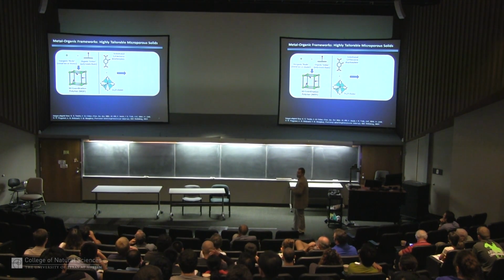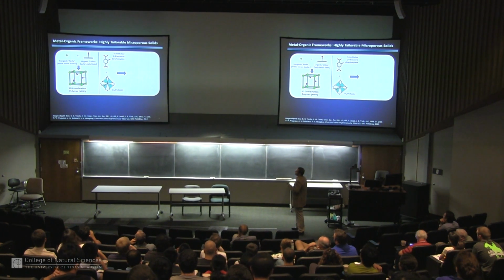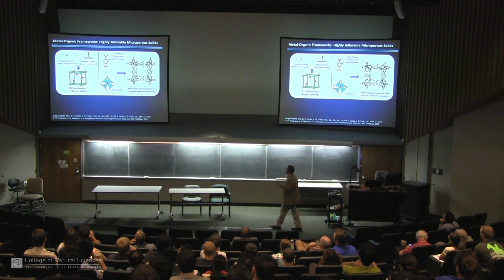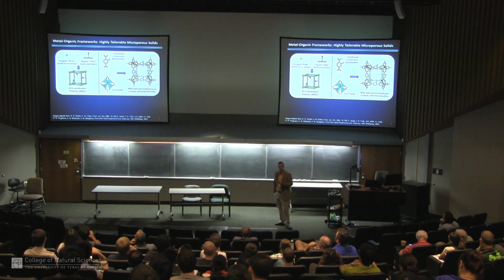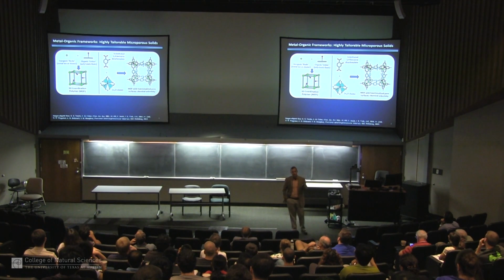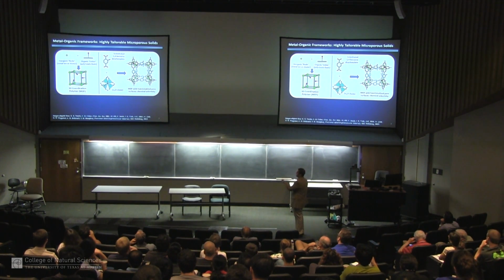And so with a little bit more chemistry in mind, here's another scheme that explains what's going on. Here's a simple ligand, a benzene-based ligand, with 2 acid groups parallel to each other on the ring, and then one substituent that, if you get the chemistry right and use the right kind of inorganic nodes, you'll only get bonding between these sites, not this one. And so you can make a porous material, which is crystalline, so it's really easy to study by X-ray diffraction. We can understand everything about the structural characteristics of the material.